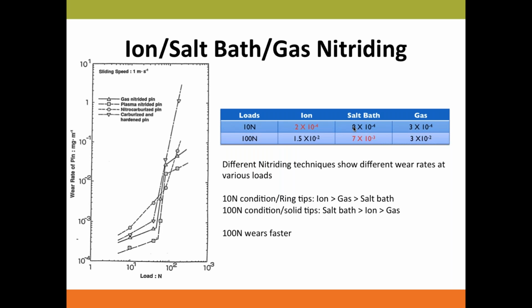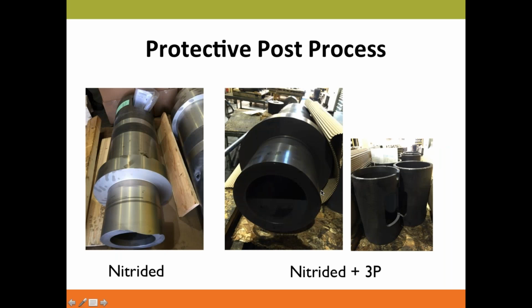What that means is, for your sleeves, there might be a difference when you use a ring type of plunger tip or solid type of plunger tips. Because with a solid type of plunger tip, inherently you're gonna have more force from the tip to the sleeves, and so you should see, according to these wear resistance indexes, the salt bath nitride and the gas nitride perform a bit differently because you use different tip types. And obviously, when you increase the load from 10 to 100, all three of the nitride techniques, the wear is gonna go faster.